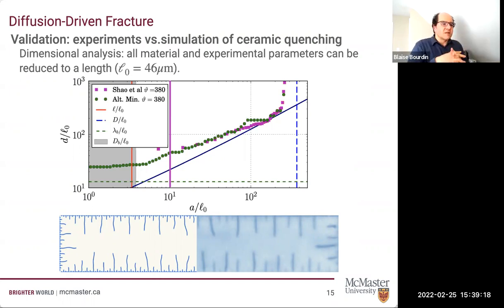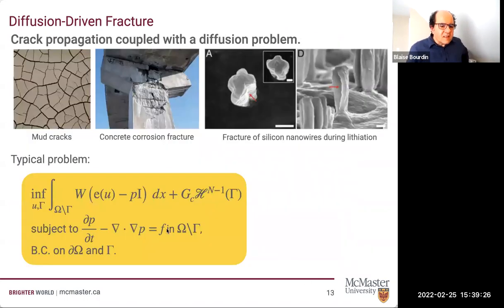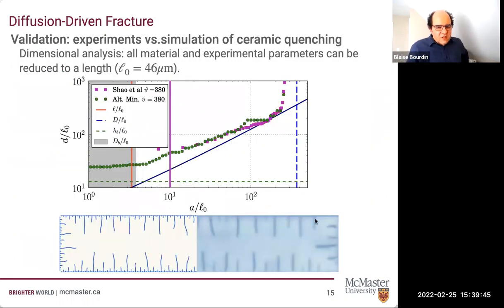So the heat flux on the crack is very small, so you can completely neglect it. Traditionally, that's the way it's been done. And if you neglect it, essentially your diffusion problem does not involve gamma anymore. So it's a one-way coupling problem. You can solve the heat equation offline and then plug the P as a source term in your fracture energy. And if you do that, to the right is actually a scan of a sample. To the left is a numerical simulation.